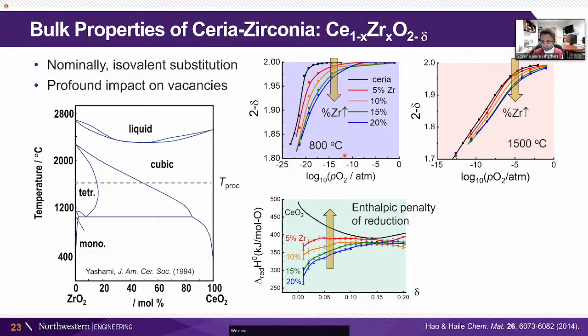We can convert this into a thermodynamic statement, which is to say that the enthalpy of reduction gets smaller in magnitude the more zirconium concentration there is. So somehow introducing zirconium reduces the thermodynamic penalty of having oxygen vacancies.